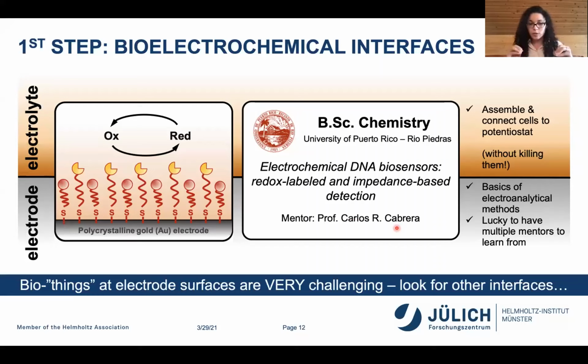But the bottom line of my work there was that bio things, when they are put onto an inorganic surface, is actually very challenging. Things die and degrade very fast because the temperature was wrong. And in Puerto Rico, the temperature was always wrong because we have humidity and it's always like 36 Celsius. So I said, okay, this is interesting and it set the stage, but I need to look for other kinds of interfaces in the long run.